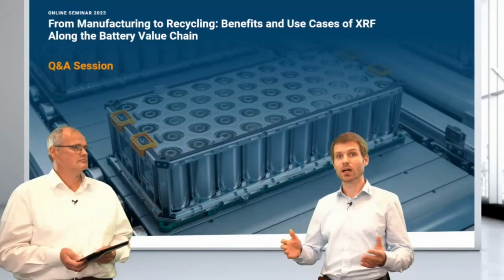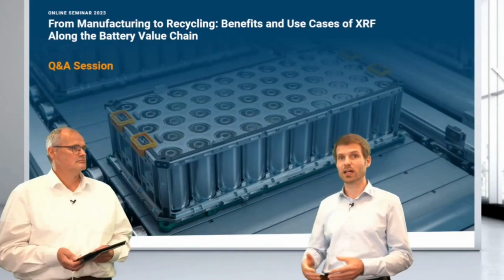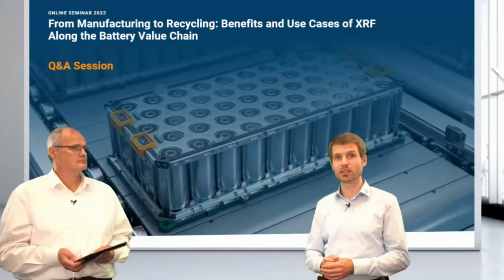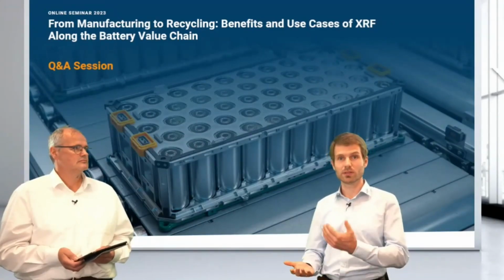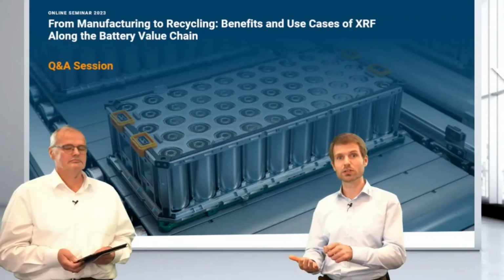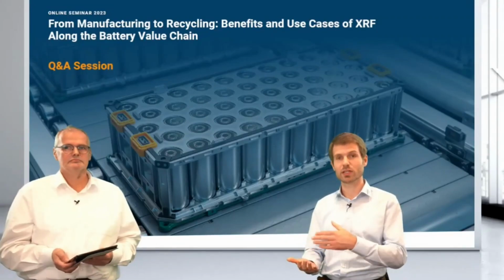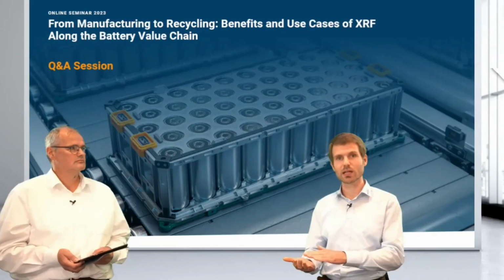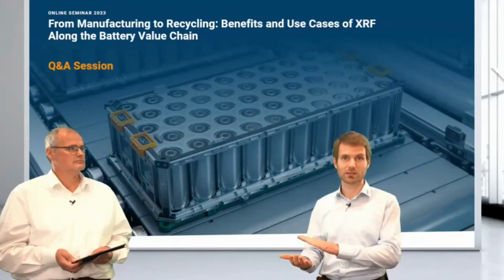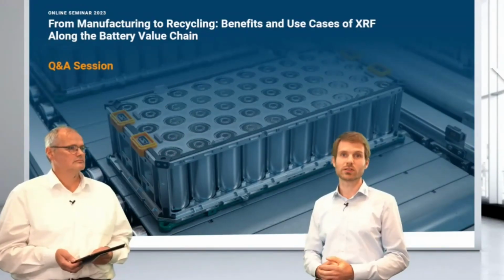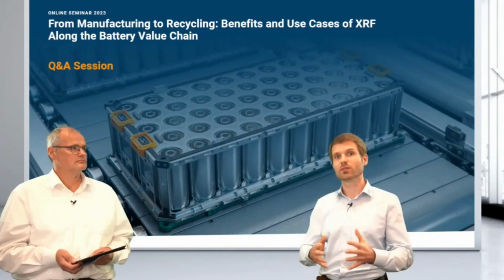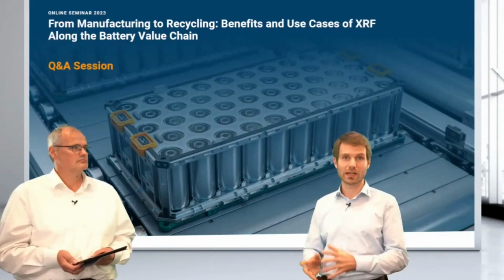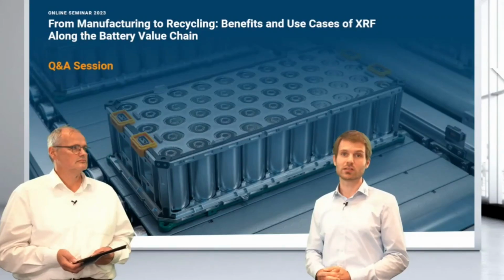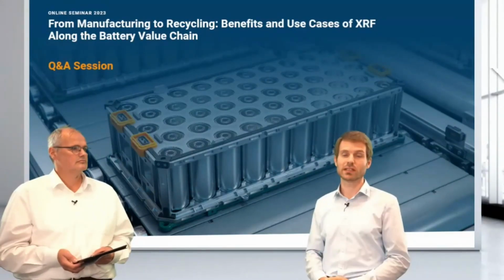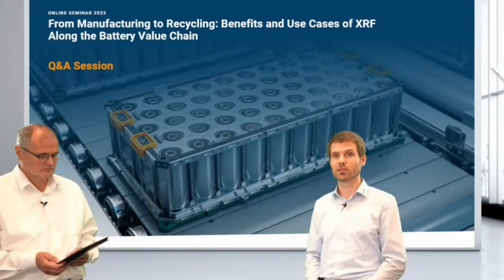of material. However, if you're in a situation where you have less sample, there are also ways to deal with it. You can, for example, smear it, if it's a slurry, on a substrate, or a little bit in a cup, or press it on some substrate. That's possible. And also for larger amounts or larger samples, there are some ways to deal with it in XRF. But that's a rough estimation.